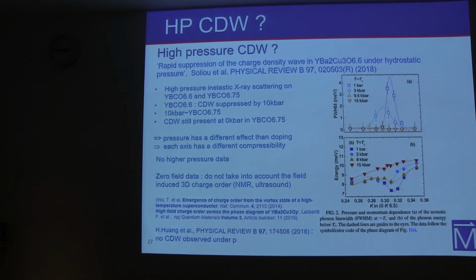And since that study does not have magnetic field, it does not look at the pressure effect on the 3D one. But you could say also the same for the 2D one, right? When you apply field, you are revealing the nature of the 3D charge density waves. So what you're basically probing with quantum oscillation is the reconstructed Fermi surface by the 3D charge density wave pocket, right? Yes.